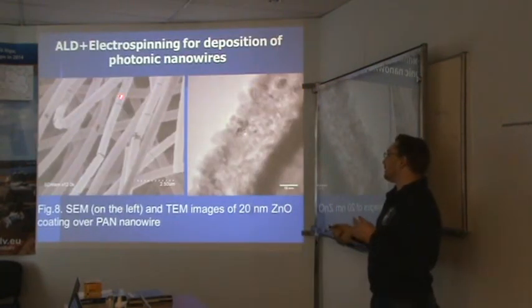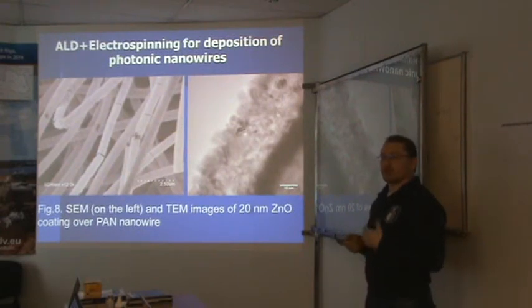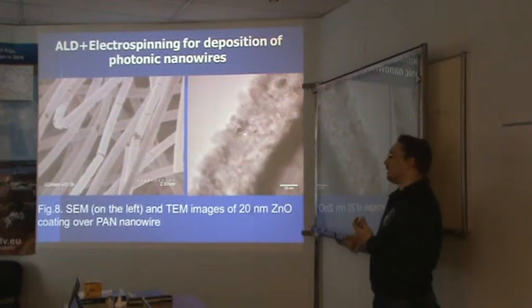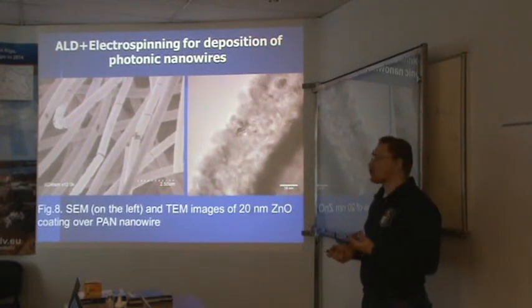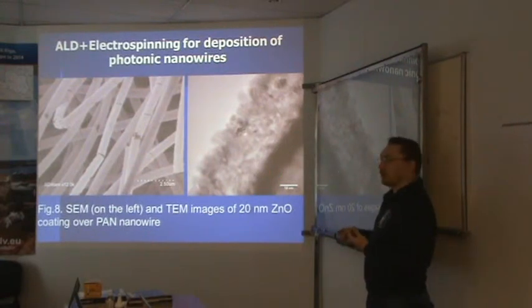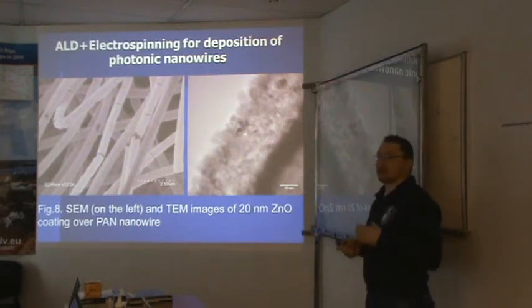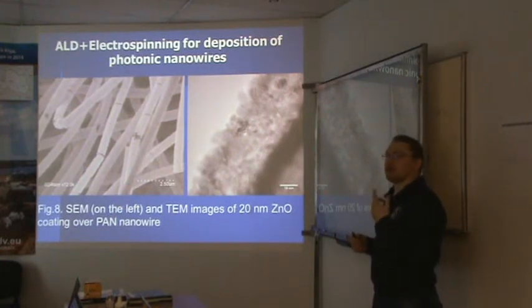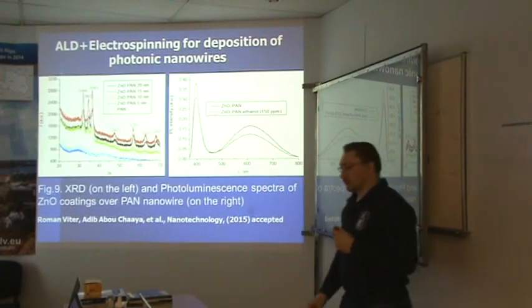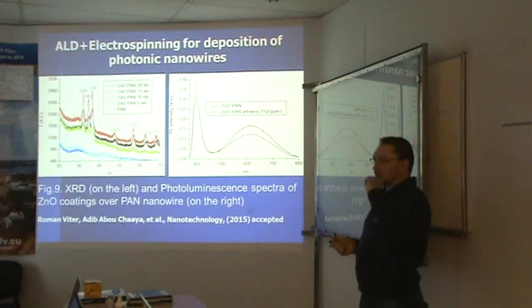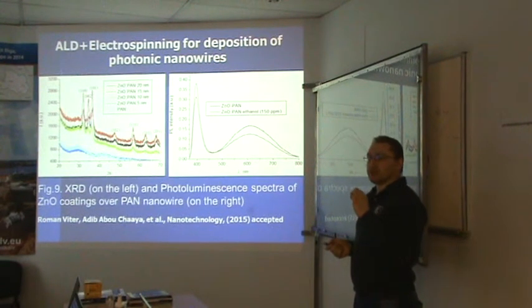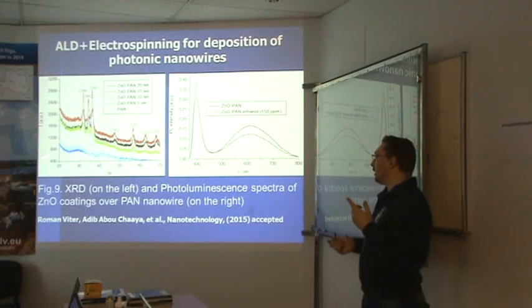Here you can see the typical SEM image of the obtained nanostructures. This is the transmission electron microscopy of this nanostructure, and this is the nanowire core, and this one represents the crystallites of the zinc oxide layer which coated this organic nanowire. We also got interesting results that even when we start with a 10 nanometers coating of this organic nanowire, we had good crystallization of the system. We observed a crystalline phase that is very important also for optical properties.